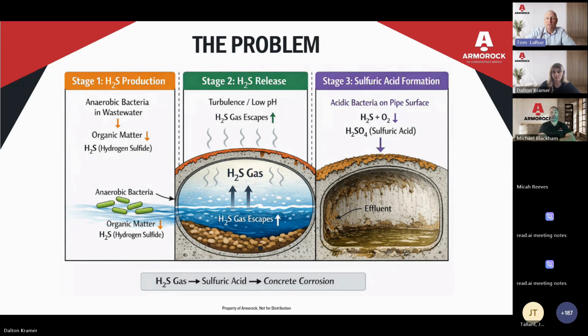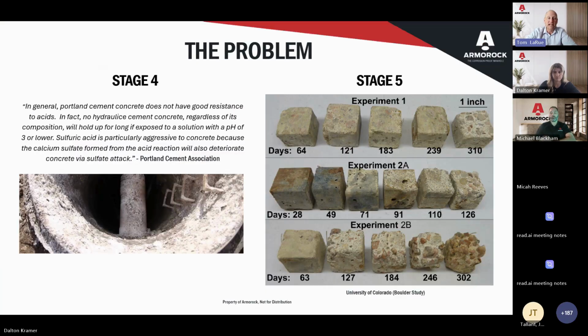So going on to step 4 is where we see the corrosion actually begin to take place, because the H2S enters the atmosphere of the system and feeds Thiobacillus, a bacteria that oxidizes H2S and secretes sulfuric acid. Sulfuric acid has a very low pH, around 1, and that is very corrosive to Portland cement-based concrete.